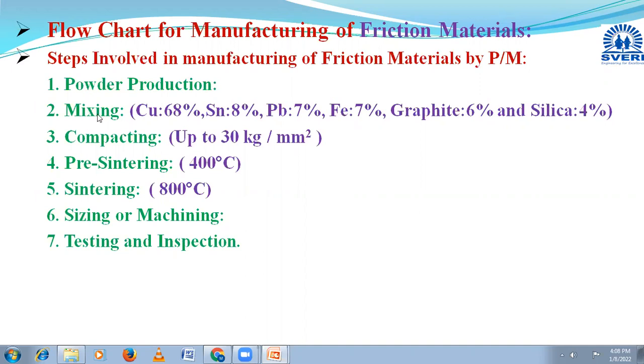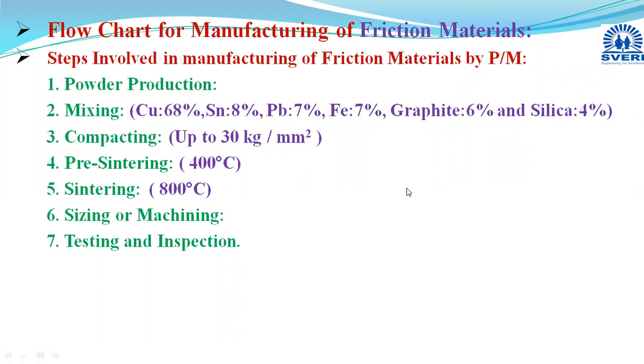Now, in this mixing stage, a uniform and homogeneous mixture of these powders is obtained. Here the percentages will be like this: copper 68%, tin 8%, lead 7%, iron 7%, graphite 6%, and silica 4%. And we can go for different mixing or blending devices. We can use a V-cone blender. Generally, a double cone blender is used to obtain a uniform and homogeneous mixture of these powders.